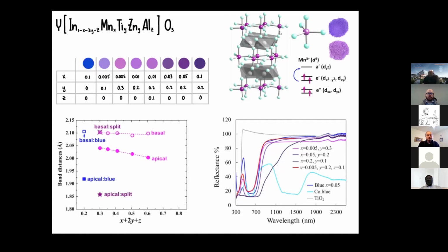how that affected both the basal distances, so that's in the plane of the base of the pyramid between the oxygen and the compound in the center, and the apical distance, and that's actually where you see where the really big changes occur. It's that apical distance. So using neutrons, he was able to determine how much that changed, and that was directly correlated to the changes in this case, the purples that they were reviewing.